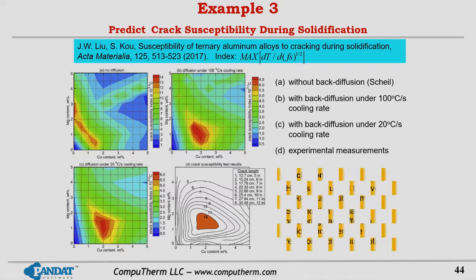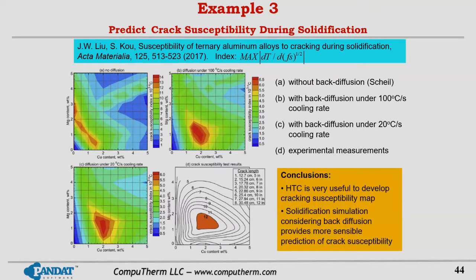So the take-home message for this simulation is that high throughput calculation is very useful to develop a cracking susceptibility map. Also, for the solidification simulation, considering back diffusion provides a more sensible prediction for the cracking susceptibility.